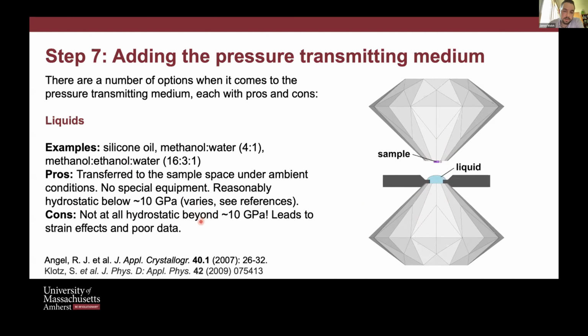I won't belabor this. Stas has already covered this basically with the same points that I did. But the pro is really that it's easy to use. But for single crystal, you really should think about whether you can gas load, because the liquids are hydrostatic at relatively low pressures, but really not beyond 10 GPa for most. That varies, but you won't find anything that you can load in this way that's really good for much more than 10 GPa. And in fact, they can often become very poorly hydrostatic above 10 GPa.